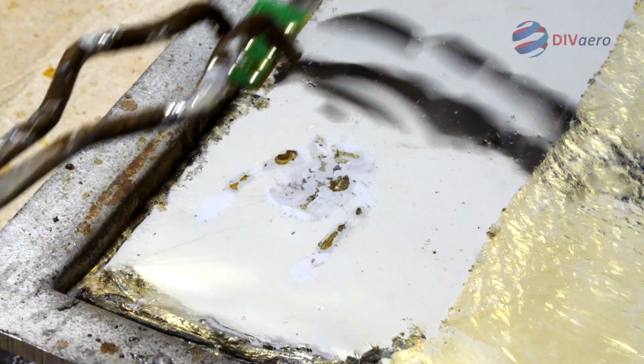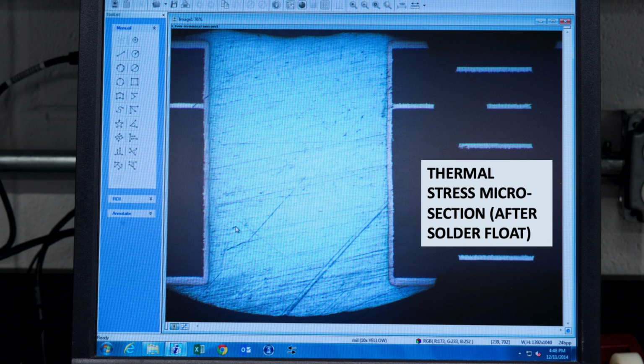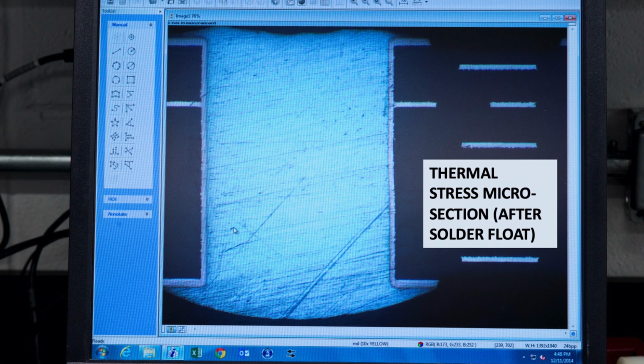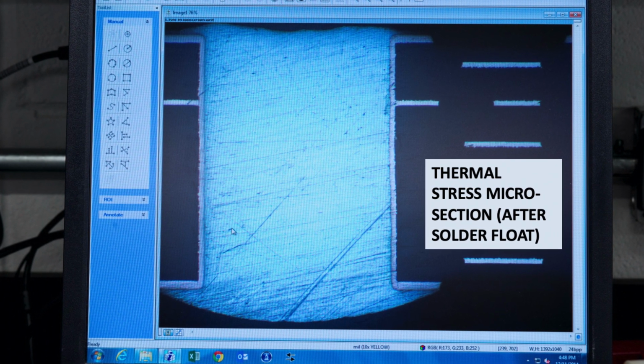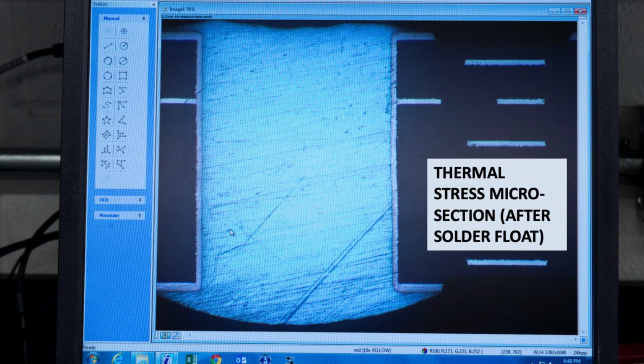The microsection shows the solder has properly wet the surface. It is wet up through the center of the hole of the PCB and flowed across the top. This particular PCB wet very, very nicely, and we know that when this is sent to the assembly process, it will perform very, very well.